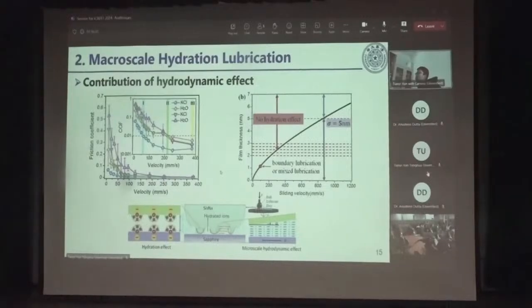And after that, we want to know whether the hydrodynamic effect can contribute to the superlubricity. The hydrodynamic effect means between the two surfaces, there's a thick liquid film, and this liquid film can separate the two surfaces. And we also do the test at different velocities. We got the curves like this, and as the velocity is high, even for pure water, the super low friction coefficient can be obtained. As the speed decreased to less than 200 millimeter per second, the friction coefficient increased with decrease of the velocity. And then we calculated the film thickness at different velocity.